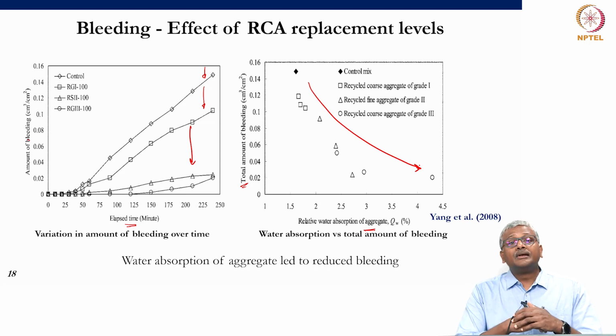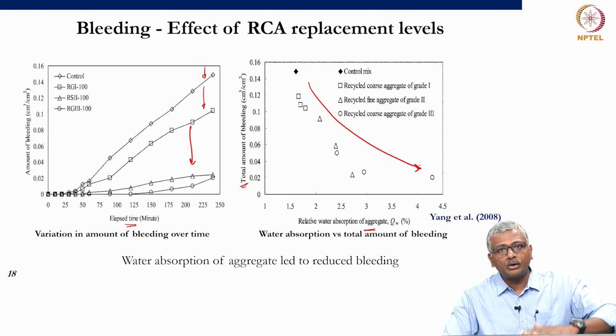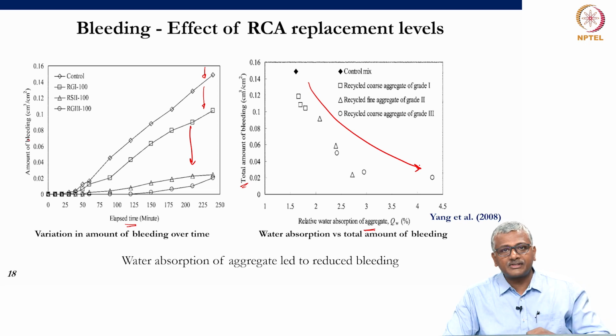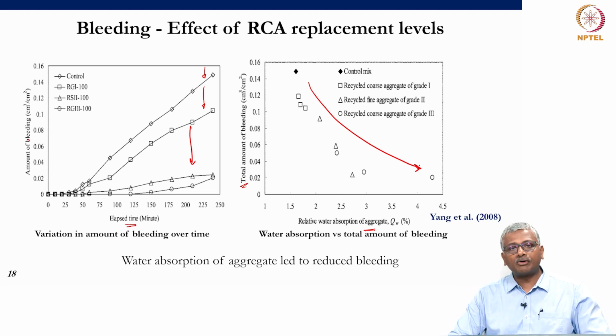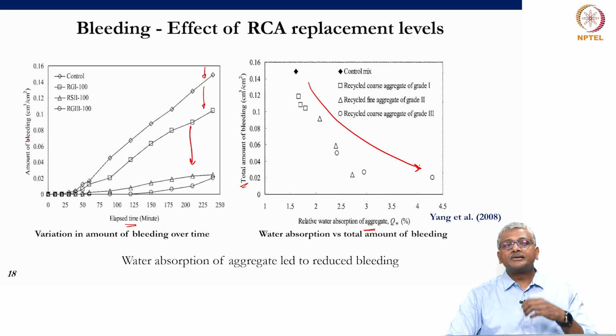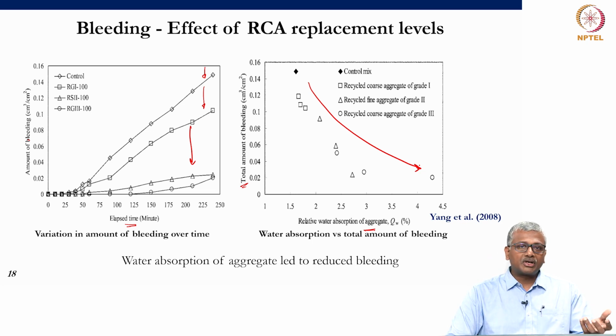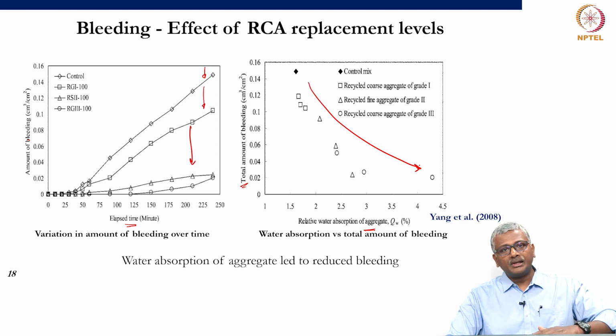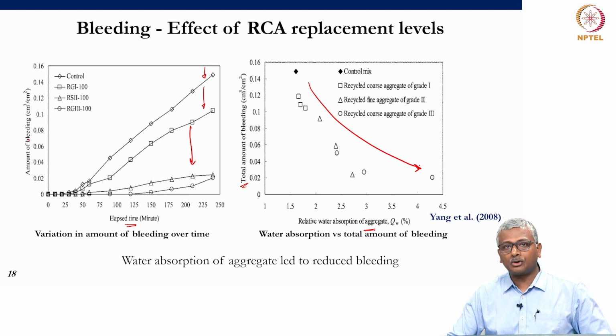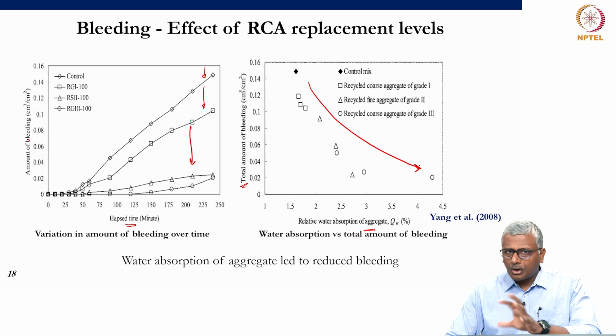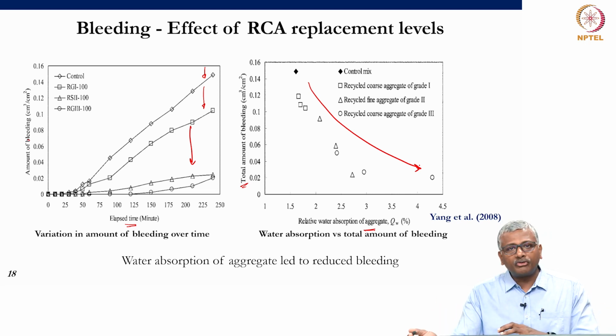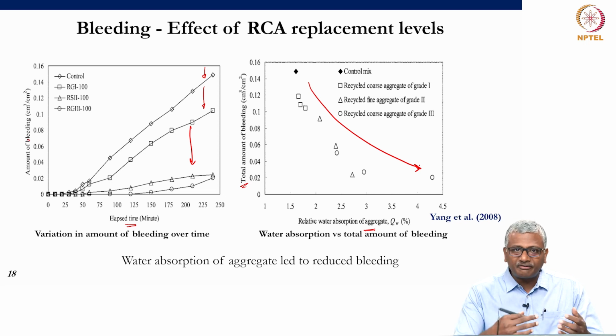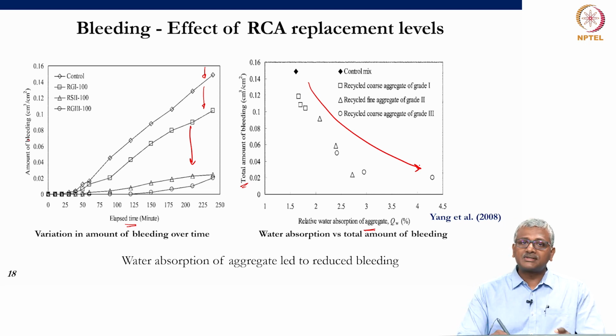Okay. For instance, when you use concrete with recycled concrete aggregate, you need to be aware that since bleed water is now not reaching the surface, you have to protect the surface early in the case of a flowable concrete, for instance, self-compacting concrete. In such cases, since the setting is slow, you have the tendency for plastic shrinkage cracking. So, if the bleeding content is reduced as compared to normal aggregate, then you need to start thinking about covering the top surface to prevent evaporation that causes plastic shrinkage cracking. Okay. So, a lot of complications can arise here and there, positive and negative, because of which you need to be wary of the fact that your bleeding characteristics are not similar when concrete is prepared with recycled concrete aggregate.